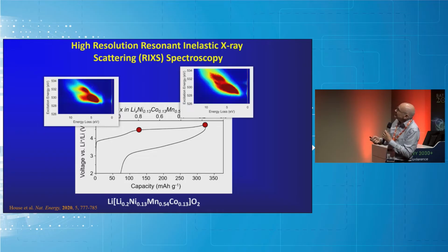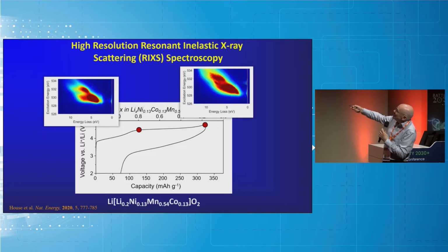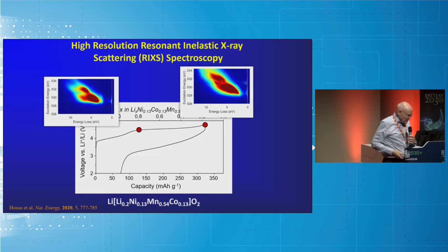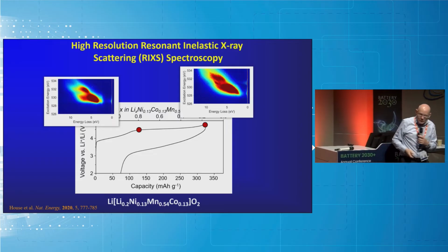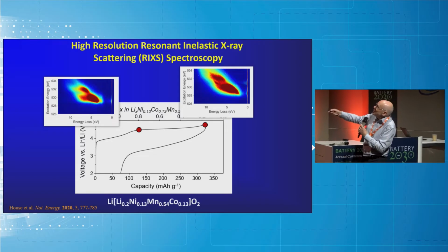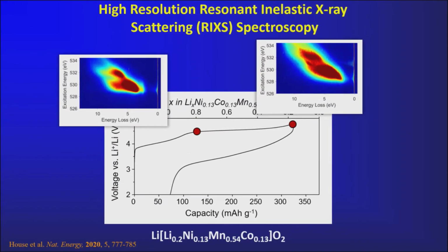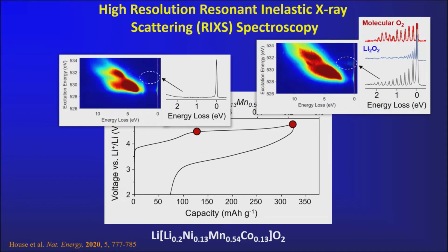This is the situation at the end of the plateau when we've oxidized a lot of those oxide ions, stripped electrons from them. And if you look at this, there are some changes here and here. But if I blow up this region here, or these regions in both cases, this is where you see the significance of the change that's occurring. There's nothing in this region before we start removing electrons from oxide ions. But after we do so, we get this series of peaks here.